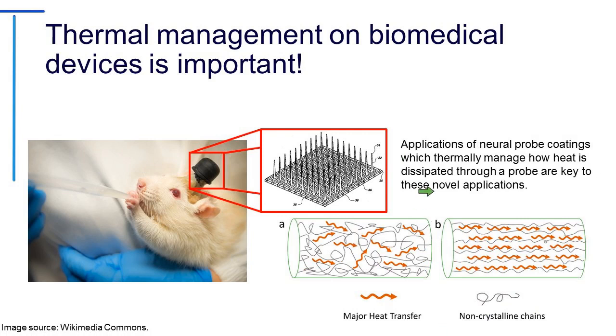So some of the applications towards this, what is currently being investigated in industry and in academia, is looking at coatings of these neural probes, specifically coating the Utah array with polymer-type materials. Polymer materials are ideal for this because they can mimic the extracellular matrix, minimizing glial scar formation by having a compliant material, which is also highly water-containing, but also at the same time we can tune the thermal properties by the way that we process the coating, or the polymer coating, onto the surface of these probes. By tuning the orientation of polymer chains, or by crystallinity, we can actually tune the thermal